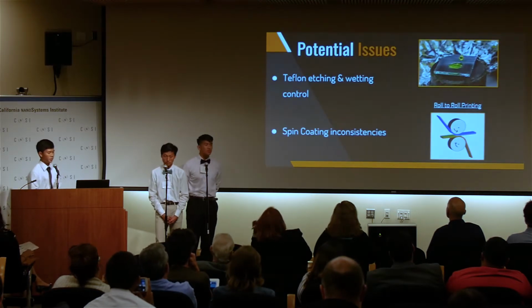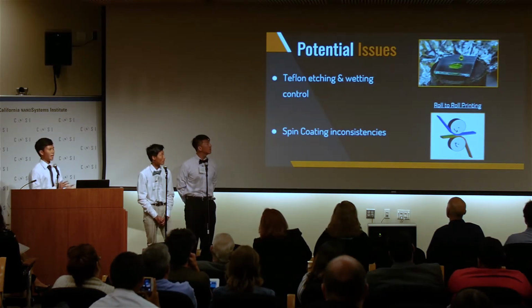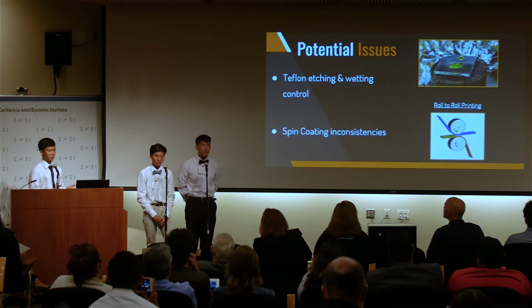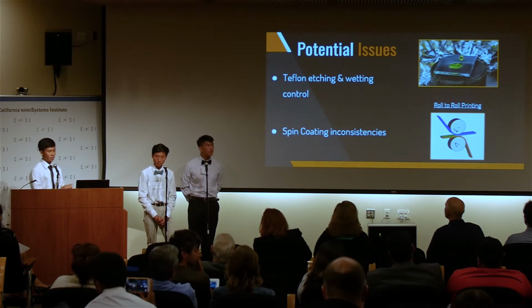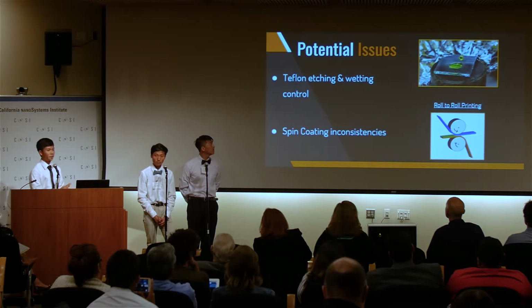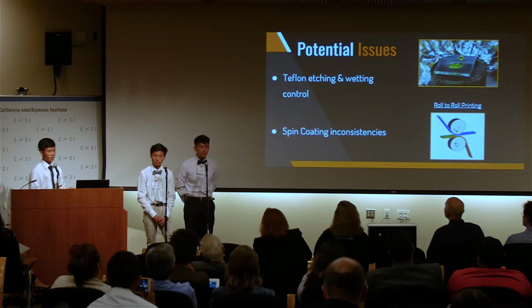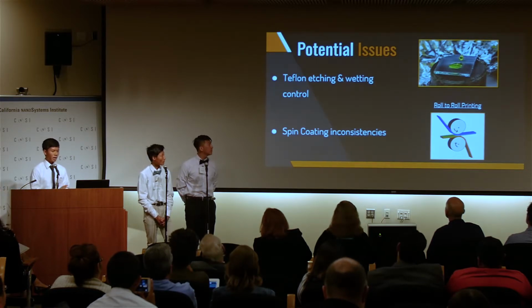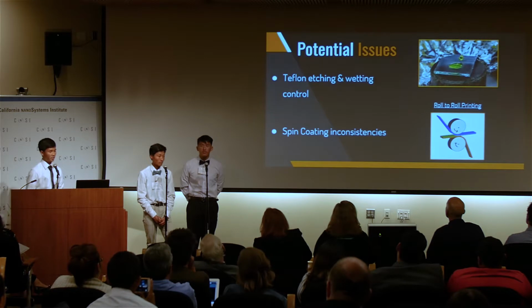So some potential issues. When you plasma etch Teflon, it actually makes it super hydrophilic, which is something we don't want. To counter this, we actually put a layer of super hydrophobic fluorocarbons, and that should protect it from any water. Another issue is the spin coating inconsistencies due to the lack of fine-tuning options when you spin coat it. So this is where we turn to the roll-to-roll printing technique, where you can actually choose the thickness that you want, and it's also faster when you actually want to manufacture these.